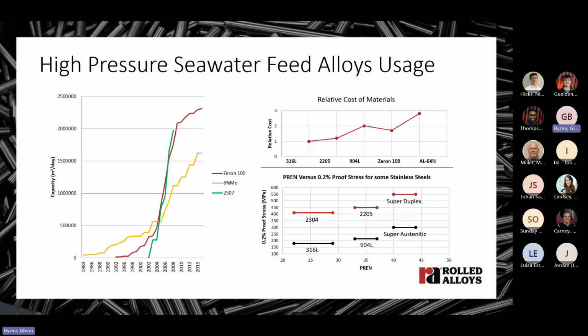So the use of 6% molybdenum alloys for high pressure seawater feed and brine reject pipework grew from 1986 onward as awareness of its good performance spread. Here I'm plotting the installed capacity of these grades of steel against a timeline. The newly developed super duplex grade Zeron 100 entered the market in 1992, with 2507 following in the early 2000s. Better technical understanding of what was required of stainless steels for seawater service, the super duplex stainless steel service history of pipes in oil and gas, in seawater cooling and fire protection systems, and as castings in seawater pumping applications, as well as its highest design strength and its significantly lower cost than 6% molybdenum alloys, contributed to its acceptance for seawater reverse osmosis applications.